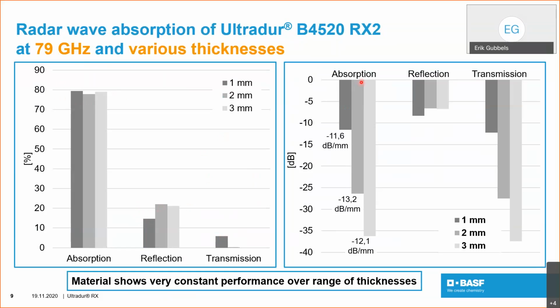Also here we consider the decibel values, and this actually gives a very homogeneous picture if you consider the thickness. The specific absorption which we look at for these various thicknesses remains somewhere between 11.5 and 13 decibels per millimeter, showing that this material has a very constant absorption over a very wide range of thicknesses.